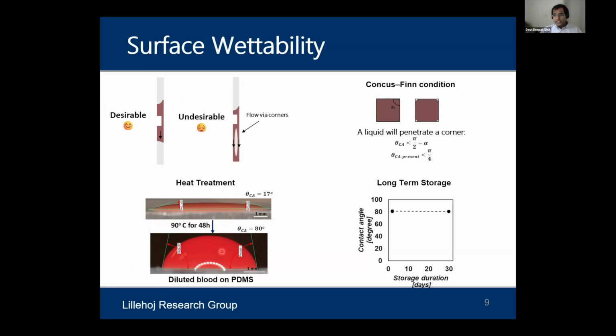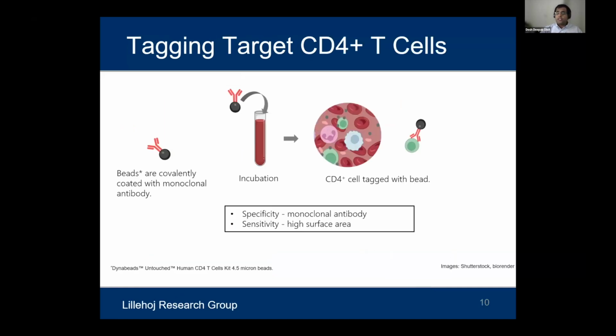So after this, we did a long-term storage test to see that if we keep this device for very long, would the recovery go in the backward direction, or would anything happen? Just by keeping it in a normal ambient condition in a closed box, we observed that there was no change in the contact angle over 30 days. So the device is fine and can be kept for long durations and has a longer shelf life.